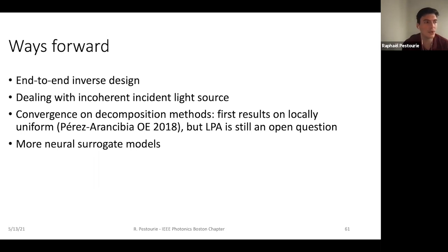If you have a single layer metasurface like the one we optimized for, there's only so much you can do. It's a very hard problem to do broadband. And if you want to do something with a large diameter, you can't really have broadband. You can have polychromatic for sure, and you can do multiple wavelengths. But if you want to go broadband, I would advise going with multiple layers.